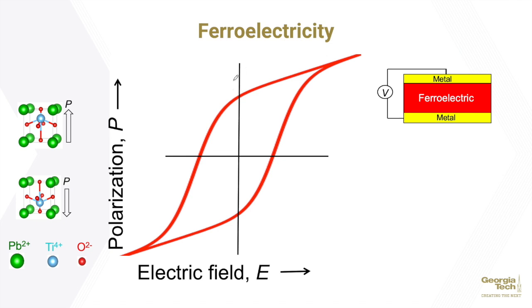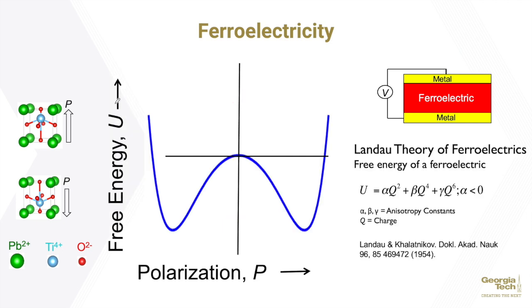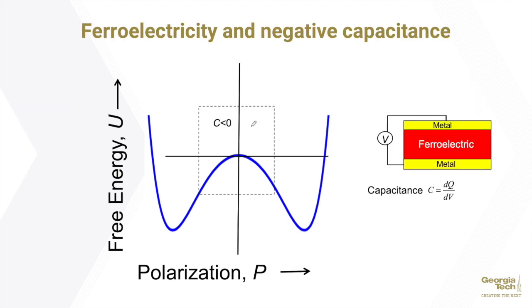Now let's dig deeper. A ferroelectric material is characterized by a hysteresis loop in terms of the polarization versus electric field characteristics. In the absence of an electric field, the ferroelectric has two remnant polarization states, and this is the basis for the non-volatile memory applications of ferroelectrics. An equivalent description of a ferroelectric material is in terms of the free energy landscape with respect to the order parameter polarization, which has a double well shape. The energy minima in this double well energy landscape correspond to the remnant polarization states. Now, things get quite interesting if one focuses on this energy barrier region, which separates these two energy minima.